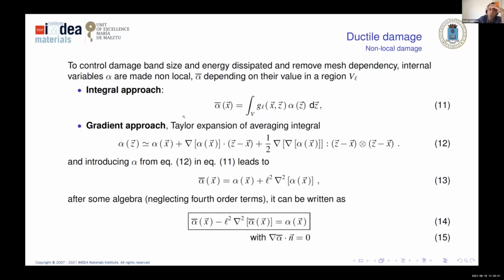This integral non-local model is very hard to integrate in a standard continuum mechanics framework. So what we can do is a Taylor expansion of the expression, and playing around with the equation, convert it into a gradient approach. In this case, the unknown is the non-local internal variable, and it can be obtained by solving a partial differential equation, the Helmholtz equation. It is nothing but the same equation that we solve in phase field, with a characteristic length and free Neumann boundary conditions.